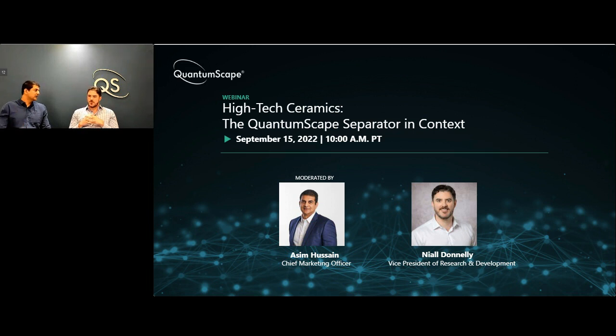Sure. So by reducing the size of your battery itself, you've now managed to reduce the diffusion distance for lithium. In a normal battery, lithium goes through the separator, but now it has to diffuse through all the anode compartment containing all the carbon and all the graphite. So it has another 80 or 100 microns of diffusion to get to access all that anode storage. In the case of the QuantumScape battery, you are depositing lithium right as soon as it exits the separator. So it has no more distance to travel. The lithium is deposited right at the anode interface.